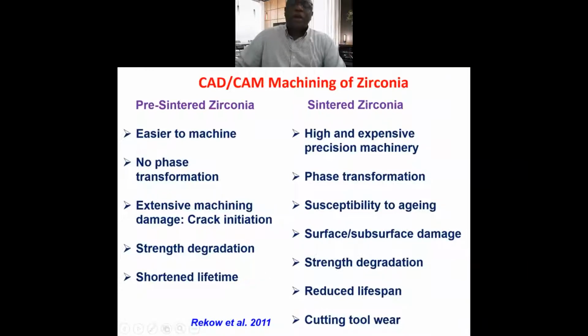For CAD/CAM machining of presintered zirconia compared to sintered zirconia, presintered zirconia is easier to machine, and there is no phase transformation. However, it comes with a price, which is extensive machining damage. There will be cracks, and even the pores are initiation sites for cracks. Because of that, there will be strength degradation and a shortened lifetime of the restoration produced. Sintered zirconia can be machined, but using high-precision, expensive machinery, in a process known as ductile mode machining.